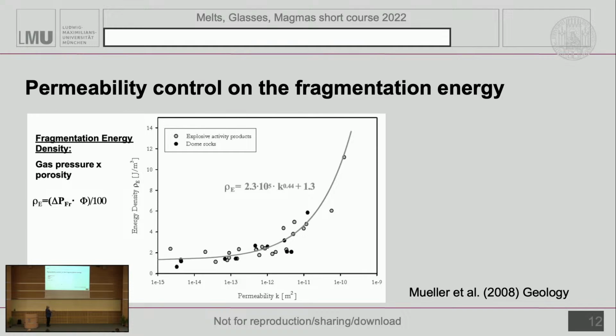But when we go to the right, what essentially happens in these experiments is the gas loss through permeable flow outruns the need for fragmentation to release the pressure. So essentially we bleed away the driving force for fragmentation through the existing permeable network of bubbles in the rock. And we should recall here that all volcanoes are degassing all the time, uninterrupted. In fact, you can look at a volcano as a degassing factory of the Earth, and you can look at an eruption as an industrial accident during the degassing, where somehow the degassing has been impeded and the gas takes the mountain of magma with it into the atmosphere.